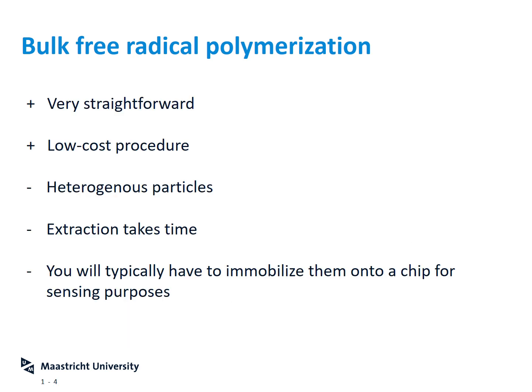Now, the benefit of using bulk free radical polymerization is that it is very cheap and very straightforward. You basically have to toss them together, wait, crush them, extract them. It's not really very difficult. The problem is that you get very heterogeneous particles. The particles will differ a lot in size and shape, and you can then pre-select them somehow by sieving them off to the desired particle size, but they will still have a very heterogeneous shape, and they will also have a very heterogeneous affinity for their target, meaning that some parts of the mixture will bind more target than other parts of the mixture, which is of course a disadvantage.